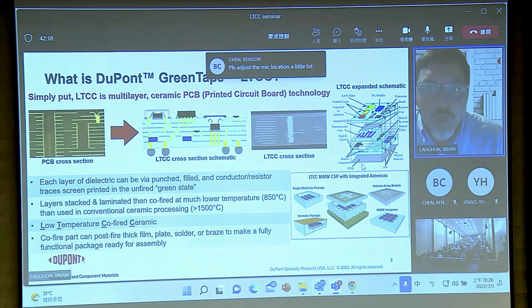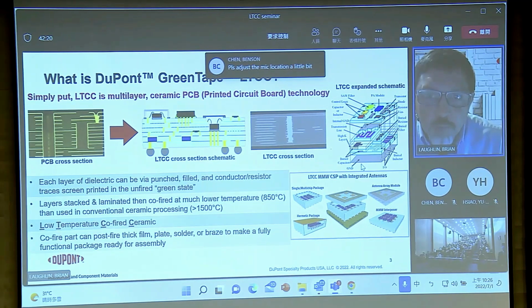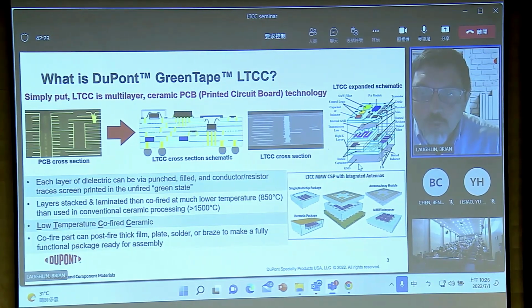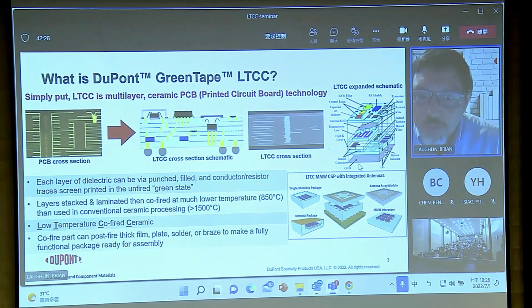So first, what is DuPont green tape LTCC? It is a product that we sell. It's a dielectric ceramic tape that we sell in the unfired state. You can punch vias, fill them, screen print conductors or resistor traces in the XY plane, all in the unfired green state. You can then collate and laminate and co-fire the stack at what's a low temperature for ceramic processing. And what you get in the end looks very similar to a printed circuit board cross section.